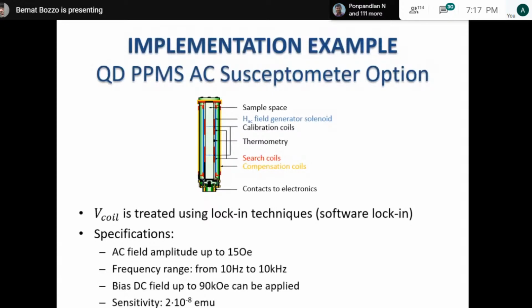Basically, as I introduced before, the voltage at the coils is treated with some lock-in techniques. In this case, we're using a software lock-in. The specification of our system is that the amplitude of the applied AC field is 15 Oe. We can work in a frequency range from 10 Hz to 10 kHz. We can apply a biased DC field up to 90 kOe. The system has a sensitivity of M prime and M double prime down to 2 times 10 to the minus 8 emu, and the working temperature goes in the range of 1.8 Kelvin to 350 Kelvin.